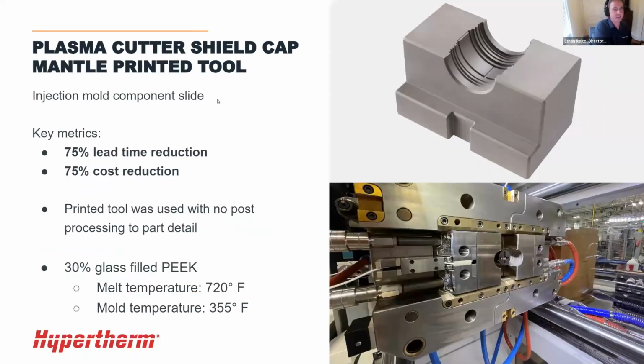So some key metrics here: 75% lead time reduction compared to, again, they would have had to outsource this tool because of the EDM work that was required. A 75% cost reduction with producing this tool. Again, the part was used with no finishing to feature detail, which is normally what people care about. They were able to leave it as is with that kind of D2 sinker EDM level finish, and they were able to mold that 30% glass-filled PEEK.